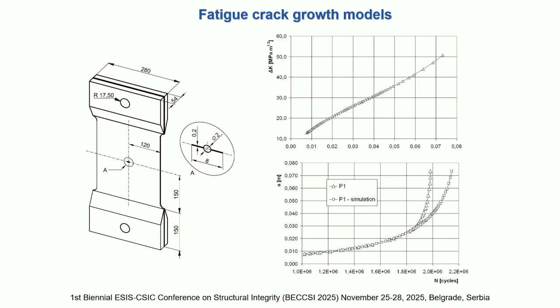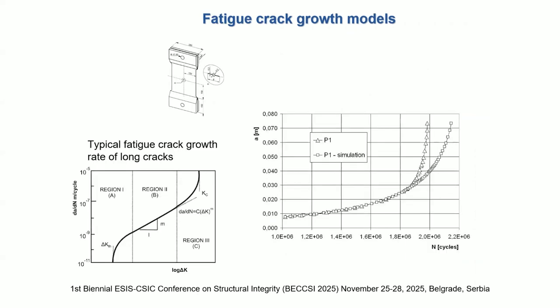And then we have experimental results like 2 million cycles and simulation results, and simulation fits very well to some 30 millimeters crack length when we are in pure Paris region. And then we have some statistics from the experiment of constant crack propagation, and simulation is still using this model, which is Paris. And so this is what I just mentioned.